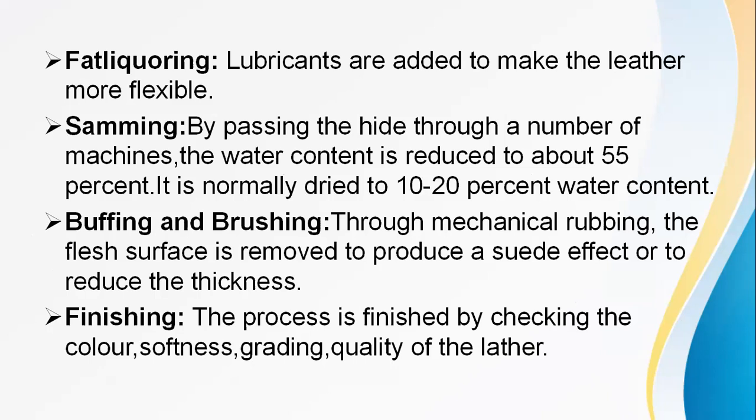Fat liquoring. Lubricants are added to make the leather more flexible. Obviously, it is one of the main requirements of leather that it should be flexible. Samming, passing the hide through a number of machines. The water content is reduced to about 55%. It is normally dried to 10 to 20% water content.